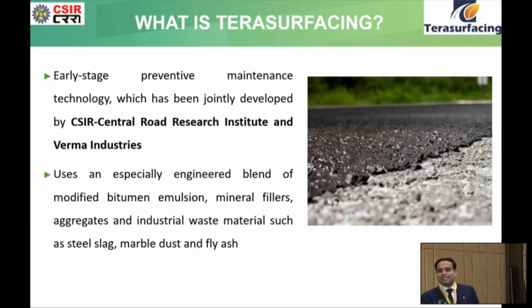The next one is the Terra surfacing technology. So I will just give you a brief about it. It's a sort of preventive maintenance technology of 8 to 10 mm thick. One of the important aspects of this technology is that we entirely use industrial waste material. It is based on fly ash, steel slag or marble dust. So in Terra surfacing, we can utilize 100% steel slag fines as a substitute for natural aggregate for preventive maintenance of the road. The thickness of this treatment is around 8 to 10 mm.